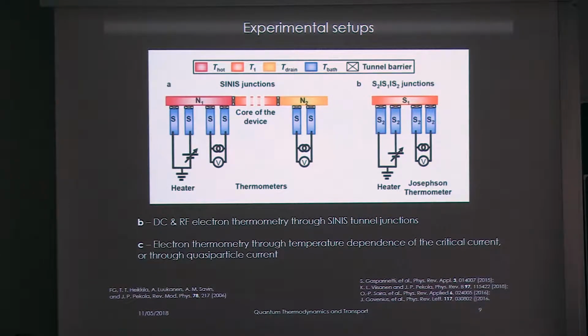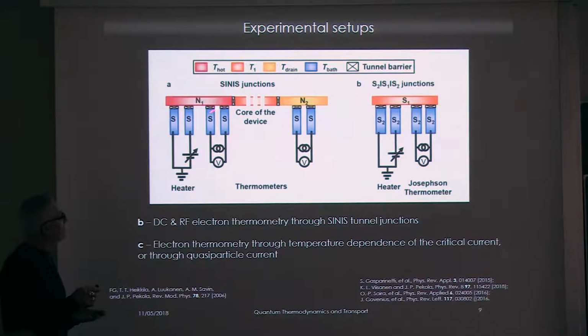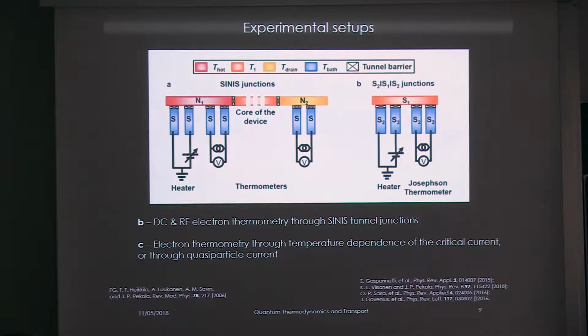In the opposite case, where we are strongly non-equilibrium, so when the temperature can no more be defined in a thermodynamic way, we can, of course, define a distribution function in the system. And with a suitable technique, we can measure the distribution function of our quasi-particle system. In that case, it can be converted to an effective temperature through a sort of Sommerfeld expansion, in order to understand what the electronic temperature would be if the system were in quasi-equilibrium.